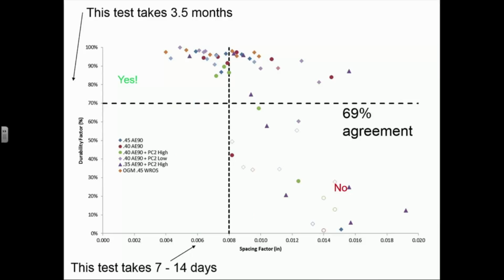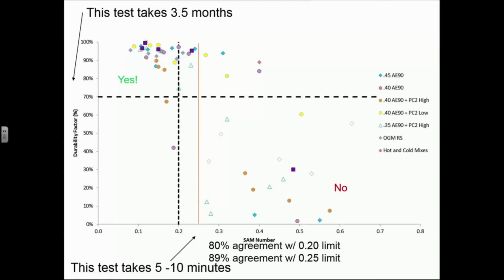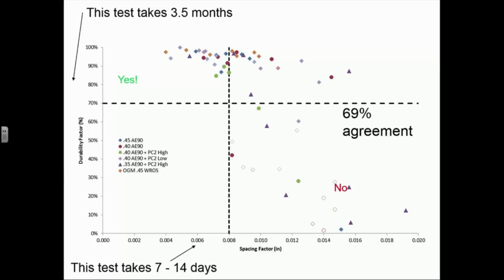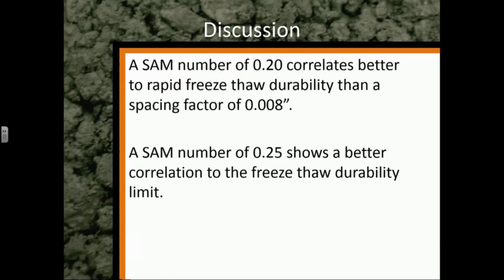Now let's talk about this mix. Here we go. If we compare durability factor, this is the results in the ASTM C666 test. Same stuff I showed you before. But instead of using SAM number, now we're using spacing factor. And again, there's the magic 0.008 inch number. And if you look at the upper left or the lower right quadrant, there's a 69% agreement. What does that mean? That means the SAM number has a better agreement. That's the stuff I showed you before. 80 to 89% agreement. This is about a 69% agreement. SAM number is showing a better agreement to freeze-thaw durability than just a spacing factor. So the SAM number 0.20 correlates better to rapid freeze-thaw durability than a spacing factor of 0.008. A SAM number of 0.25 shows a better correlation to the freeze-thaw durability limit as well.